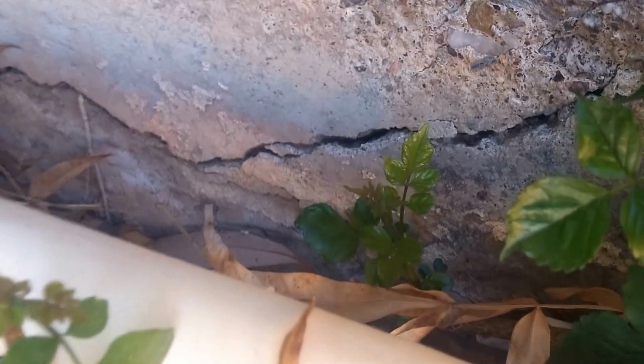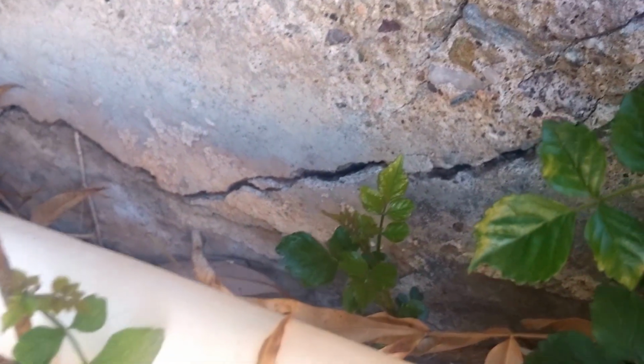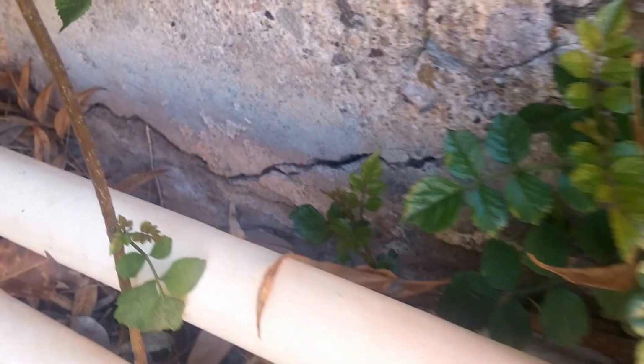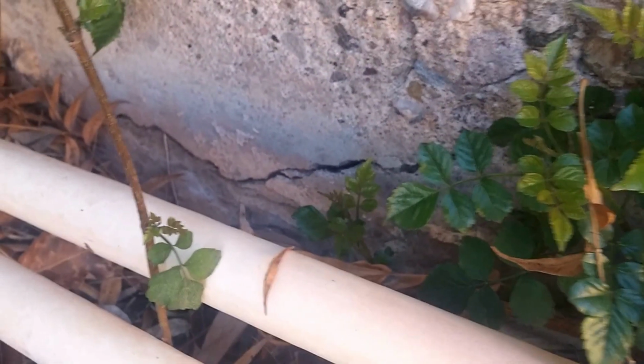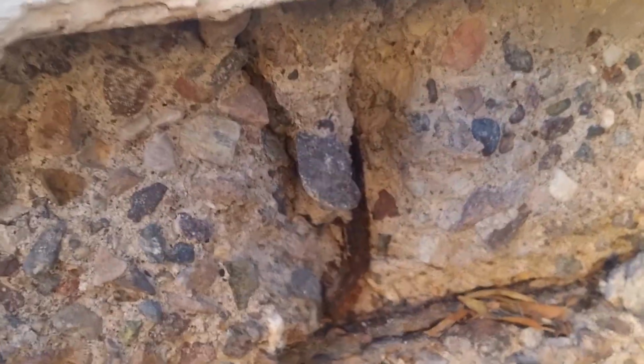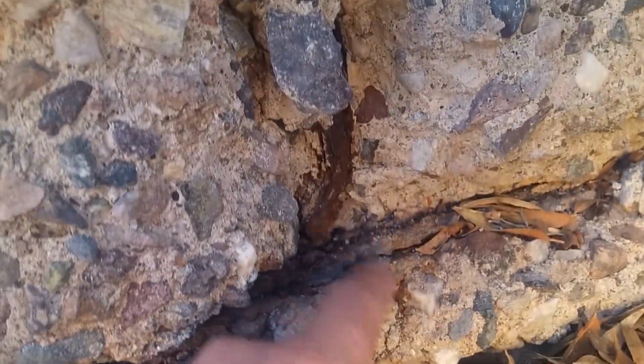That crack and fracture right there is oxidized rebar. Once moisture reaches the reinforcement, number 4 bar, 1/2 inch in the stem wall, it's going to oxidize and expand up to 5 times its diameter and size, and it's going to break out the side of the stem wall like this. And you can actually see the J-bolt right there. This is the J-bolt holding down the bottom plate of the stem wall that's behind here. This is remnants of the 1/2 inch rebar.